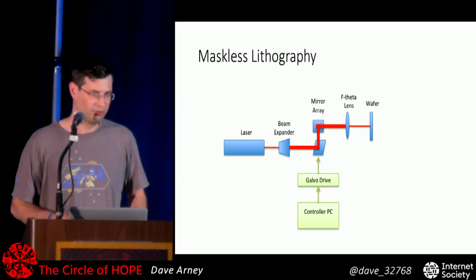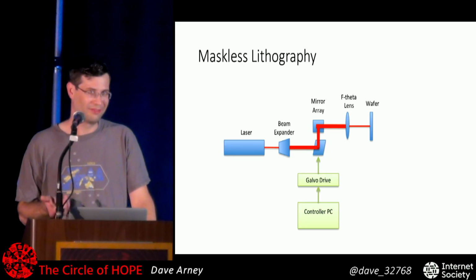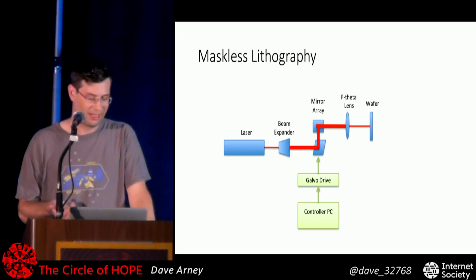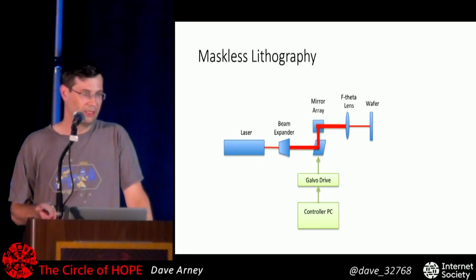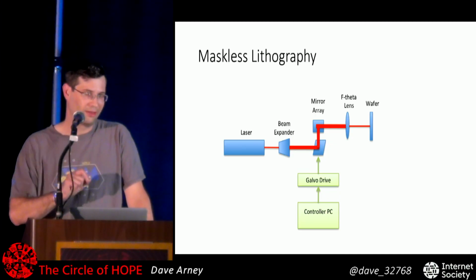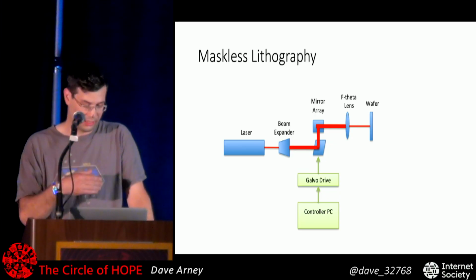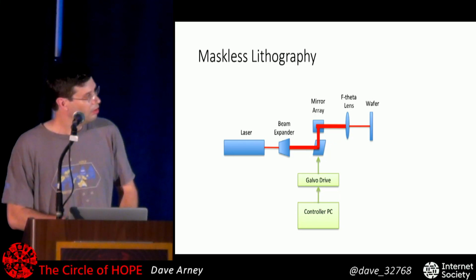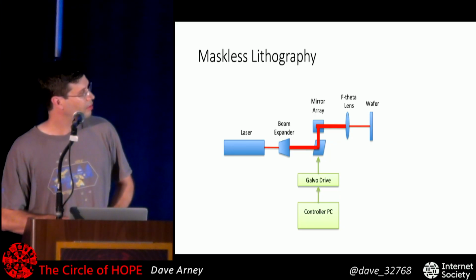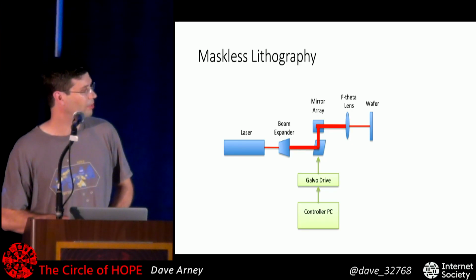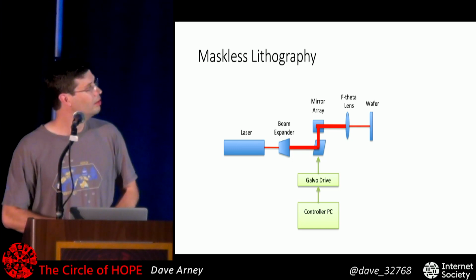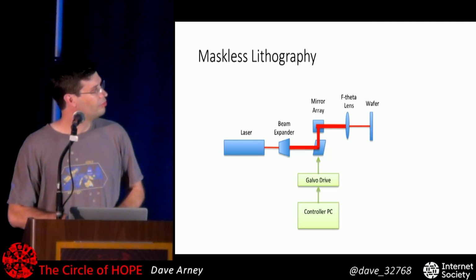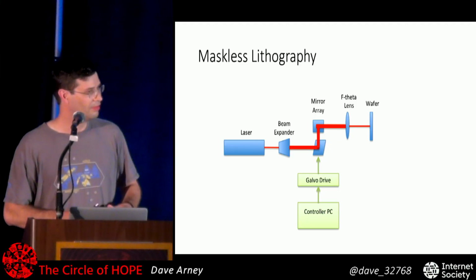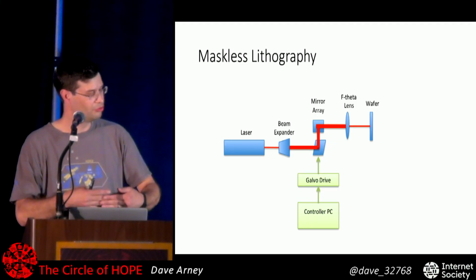probably the easiest thing to do, or the best thing to do, is set up a maskless lithography setup. So rather than using a mask at all, you get rid of that completely and use a laser to write directly on your substrate, write directly on the wafer. So you need a UV laser. You shoot that through a beam expander, because your optics down here are going to work better with a fatter beam. Put it through mirrors that steer in X and Y, and put it through a lens that then will map onto sort of a two-dimensional plane.